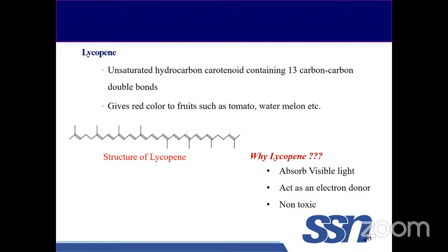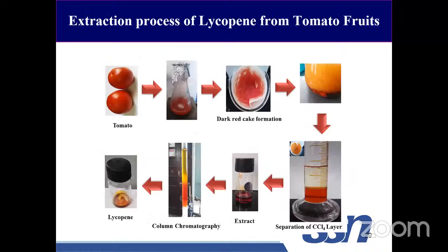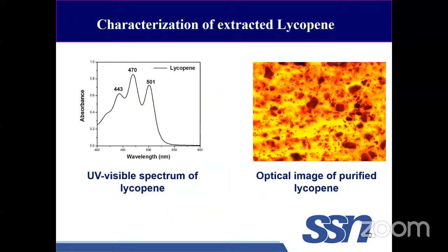So what we actually did is, we took tomato, crushed it, and filtered it, and the filter cake was mixed with CCl4 and allowed to phase separate. The separated red color solution was taken back and we did column chromatography and extracted the lycopene finally. The extracted lycopene was characterized. The peaks at 443, 470 and 501 confirm that the extracted medium was lycopene, and this is the optical microscope image of the purified lycopene. As you can see, it's completely red in color.